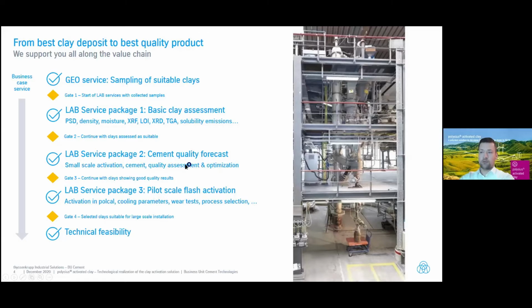Finally, if we could find the right cement quality with the available clay, then we are going over into the pilot scale flash activation. This is what you can see on the right-hand side. Our so-called Polcal solution. This is a preheater calciner system. This is in Germany. And we are activating around 1 ton of material.